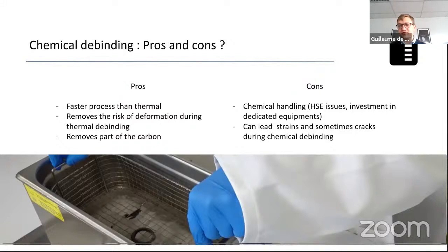On the cons, of course, you have the chemical handling. You handle solvents, which means you certainly need to be careful about health and security. You may need to invest into dedicated equipment. And also the chemical debinding can leave some strain in the material, and sometimes it can cause some cracks in the material. So that's, of course, a very efficient way of making parts, but still it has also some cons.